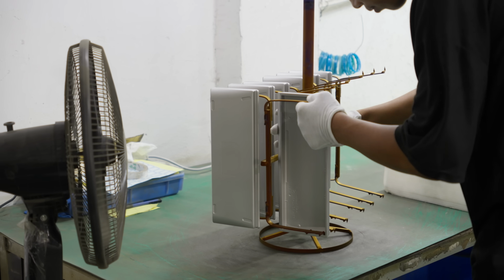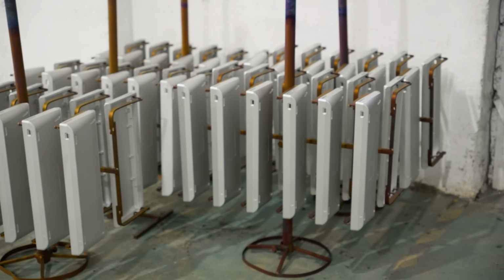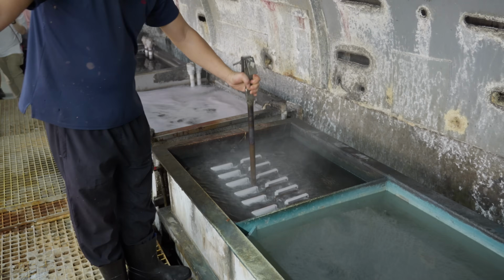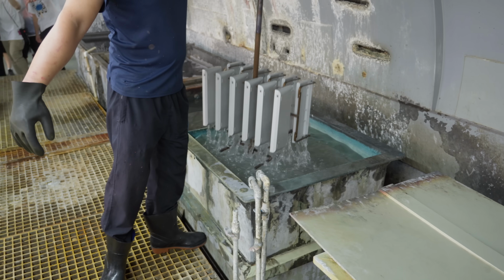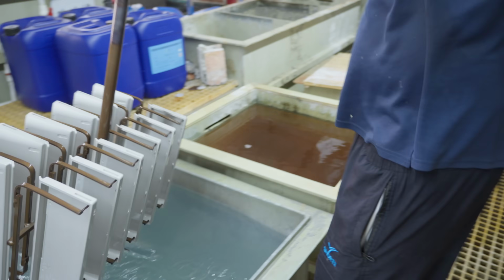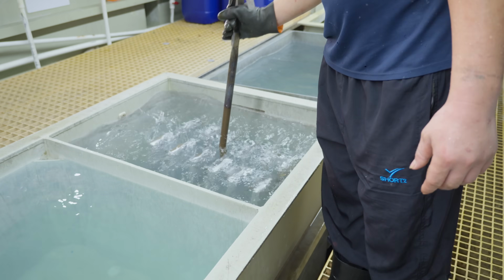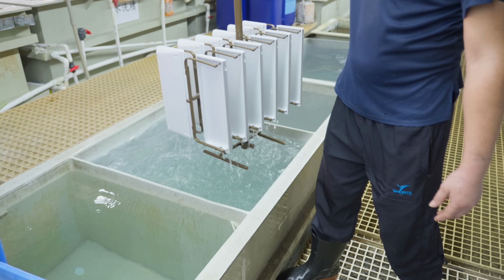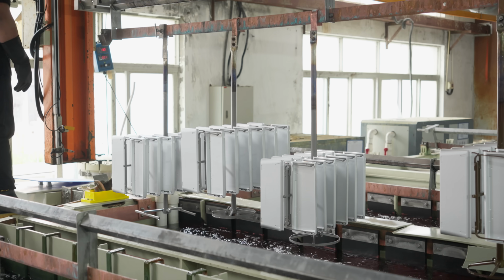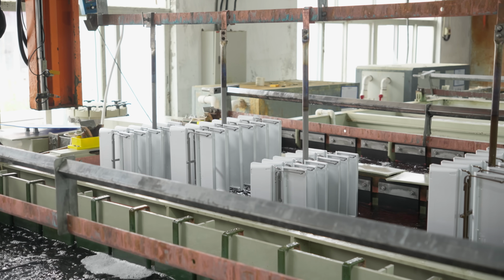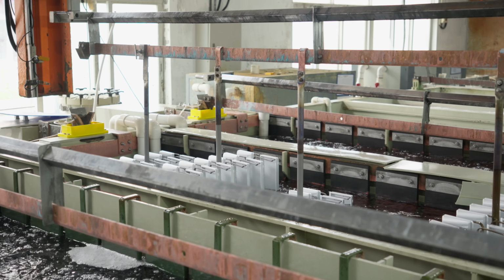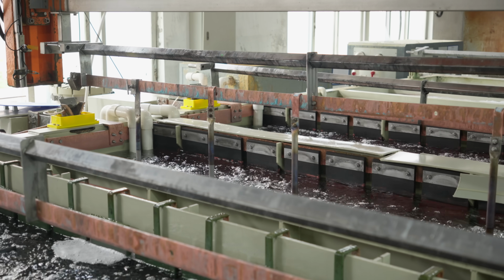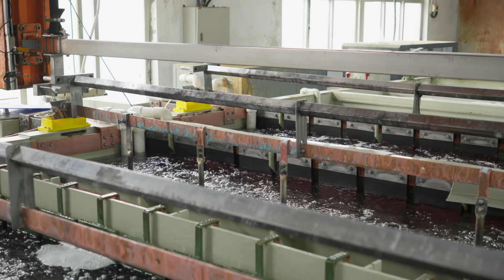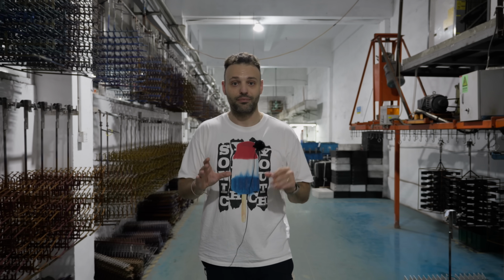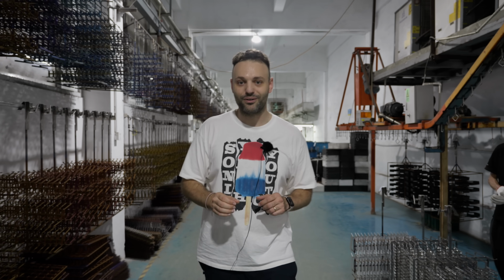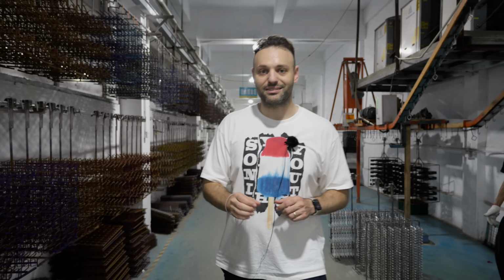Now, before it goes into the actual anodization bath itself, it needs to be prepared, and that preparation is an alkaline bath, a pH neutralization bath, and a little acid bath, after which it gets washed every time. And that helps with the shine, it helps with the feel, and then it goes into the anodization bath, which is the longest bath, for 30 minutes, and that will create that hardened, oxidized layer and imbue the color to the surface of the alumina. And that will stay there for a long time. And then you have your perfect, beautiful 60HE V2 case.